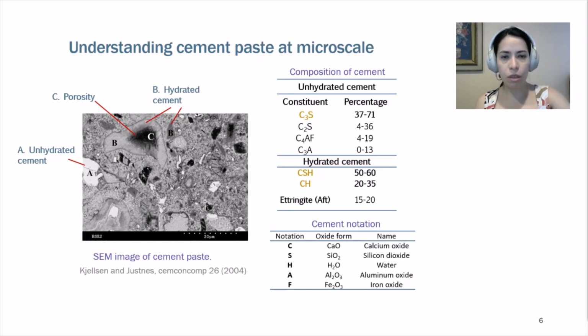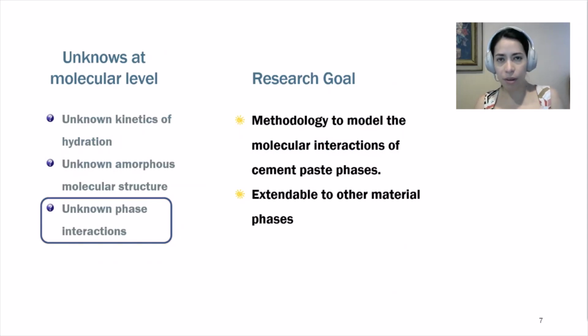So this is what we know, but there are still many unknowns. For example, it is still unknown the kinetics of hydration. We still don't know the structure of the CSH, but we know that it's mostly amorphous. And then there are no studies of the phase interactions. So if we want to start to study this composite and we want to add nanomaterials to it, we need to understand how these phases interact with each other and how they will interact with the nanomaterial.